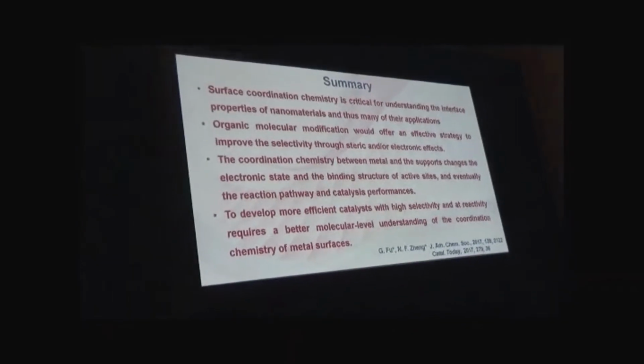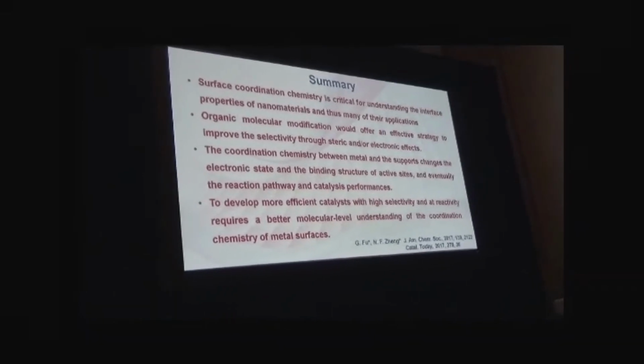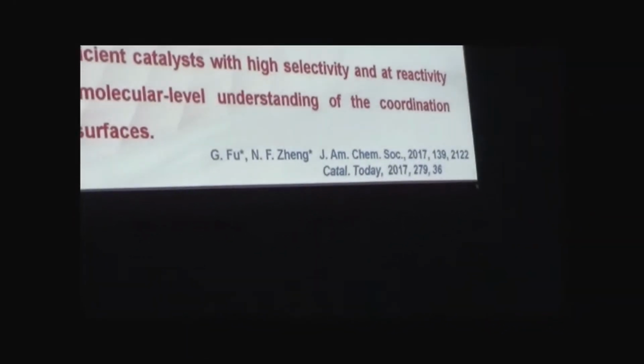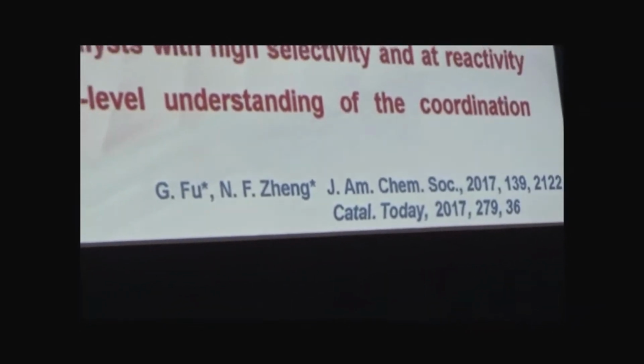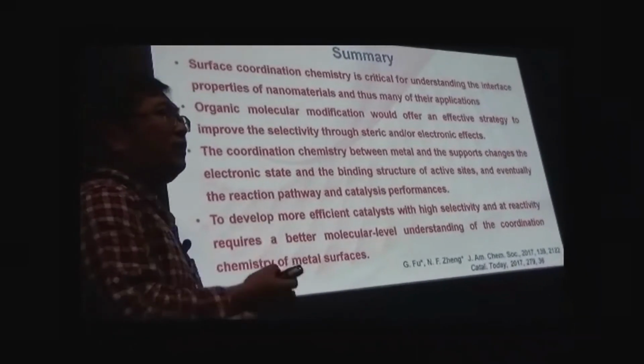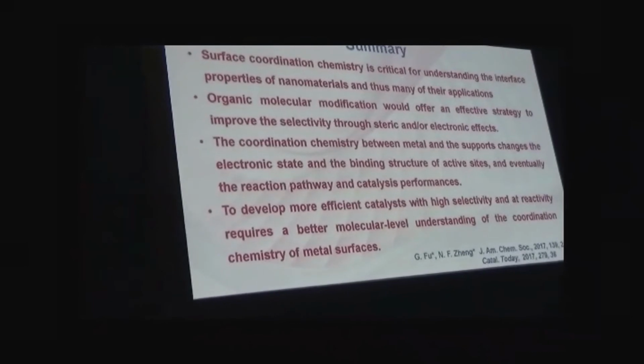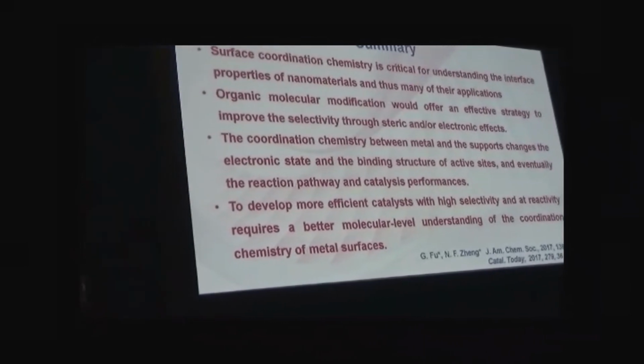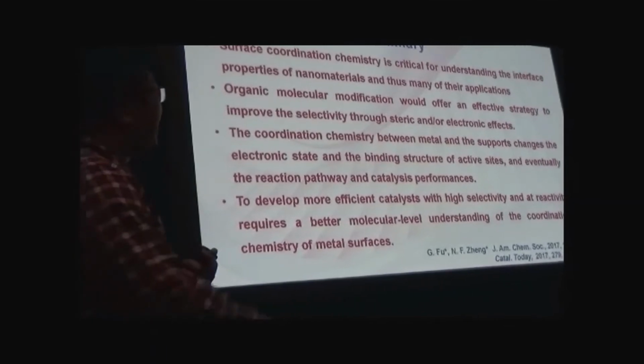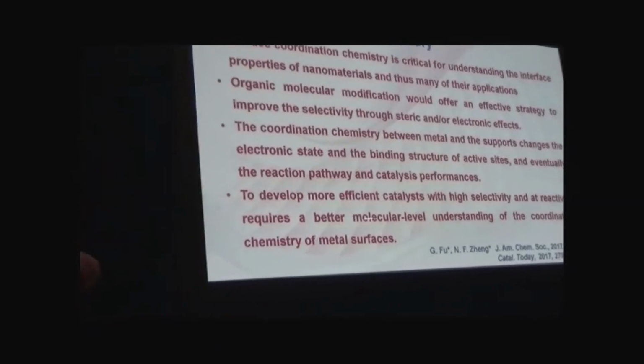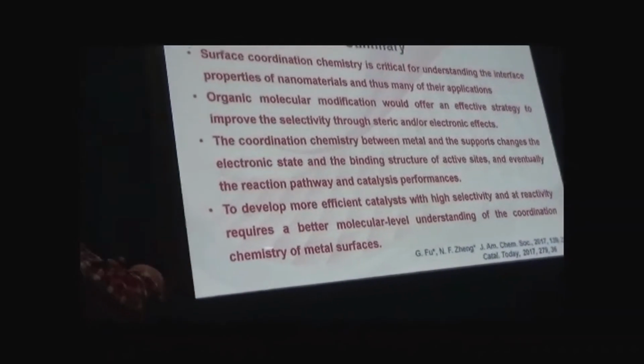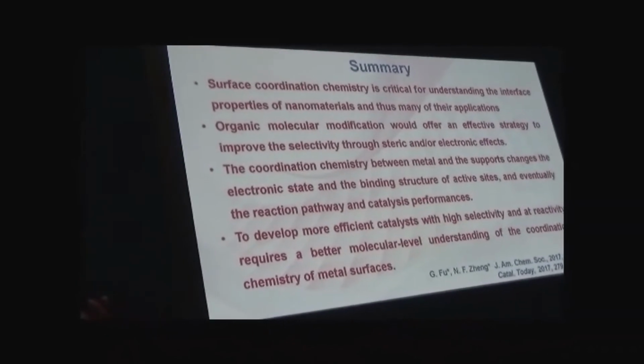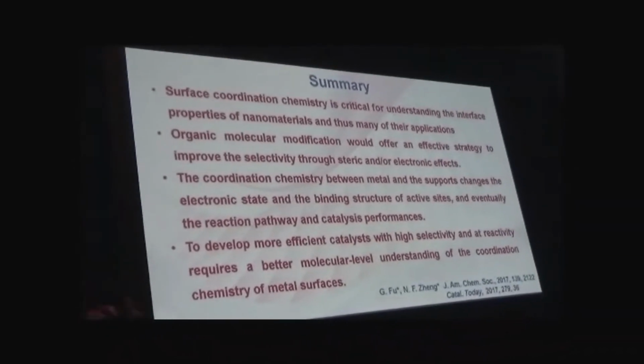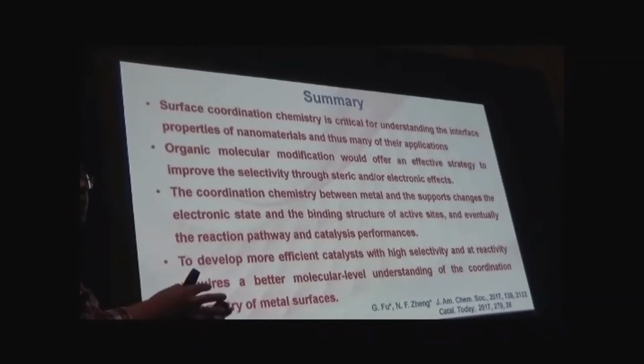Here we would like to give a summary. The first one, the surface coordination chemistry, is very important for understanding the reaction. The organic ligand modification will control selectivity through the steric way and through the electronic way. And the coordination chemistry between the metal and ligand will modify the electron state and binding structure of the active site, and even modify the reaction mechanism. To develop more efficient catalysts with high stability and reactivity requires better understanding of the surface chemistry. It requires the close cooperation between theory and experiment.